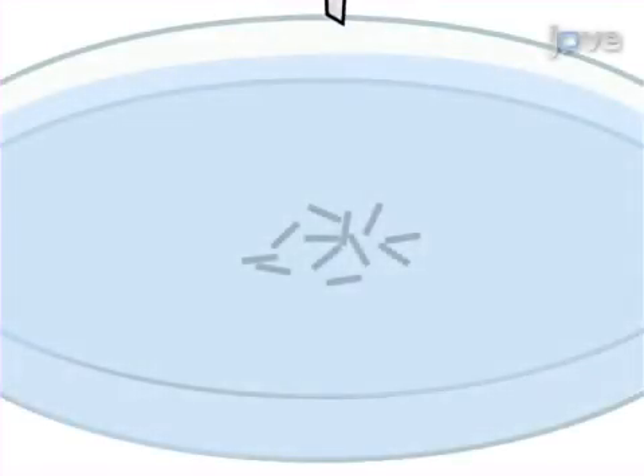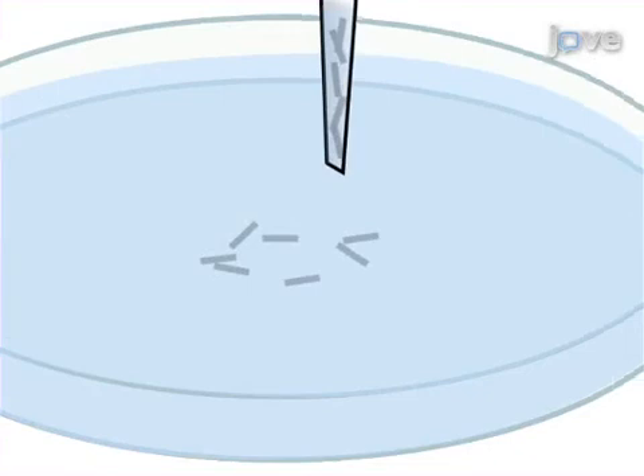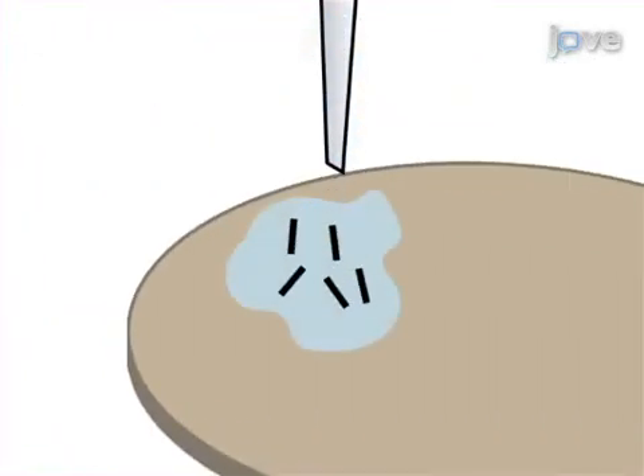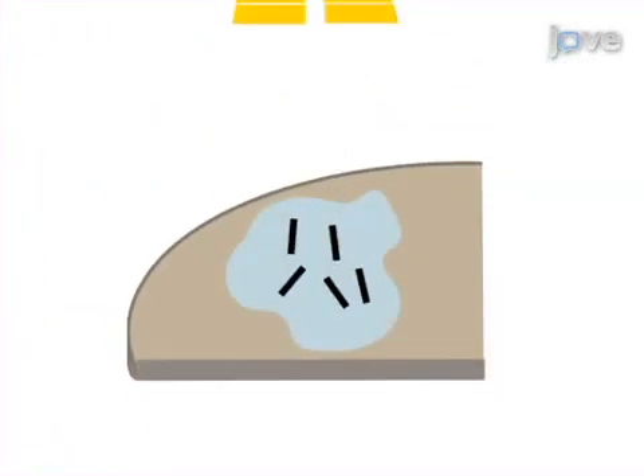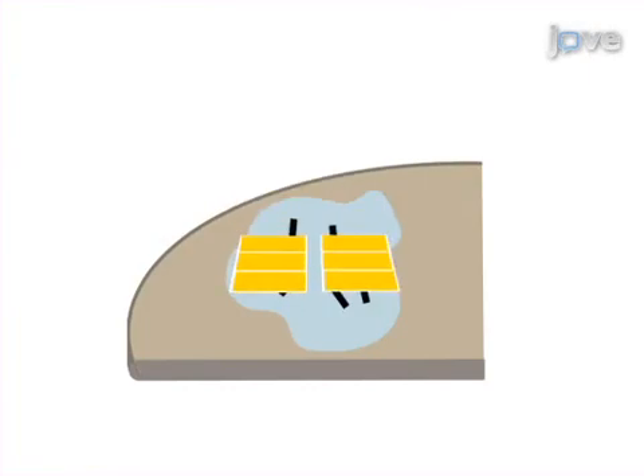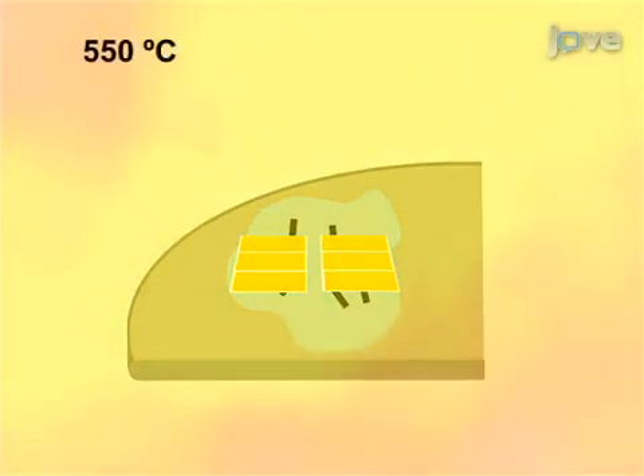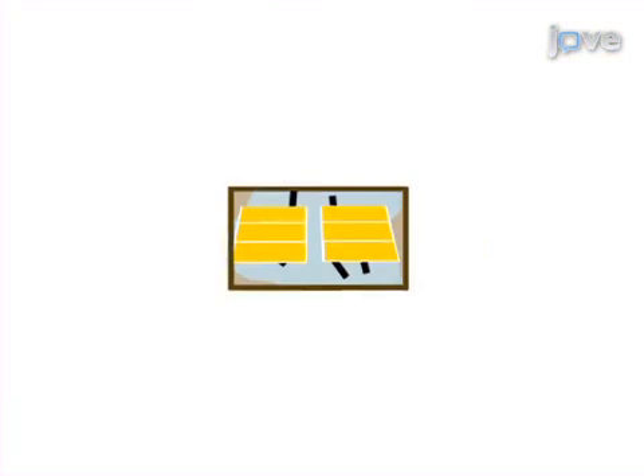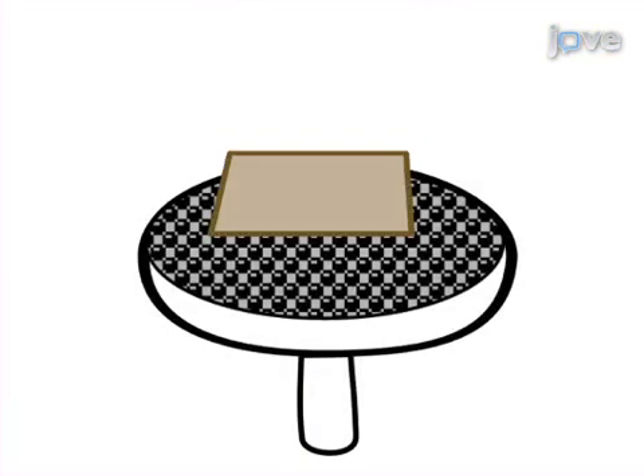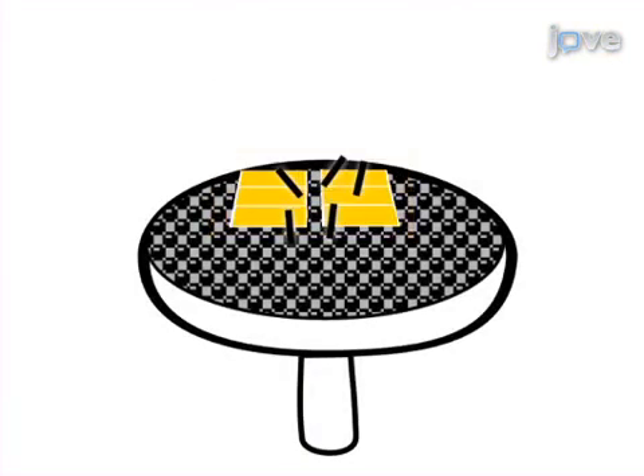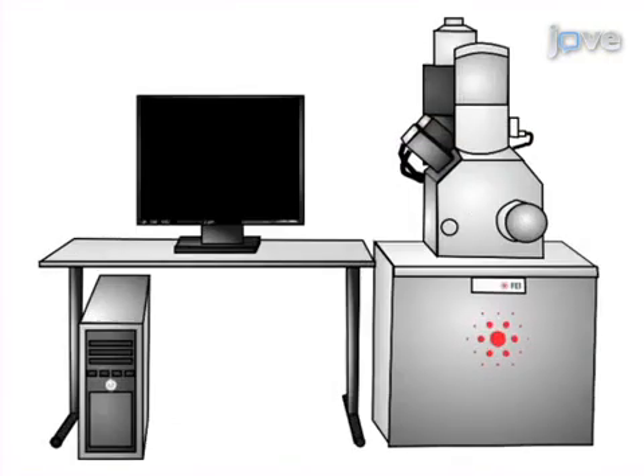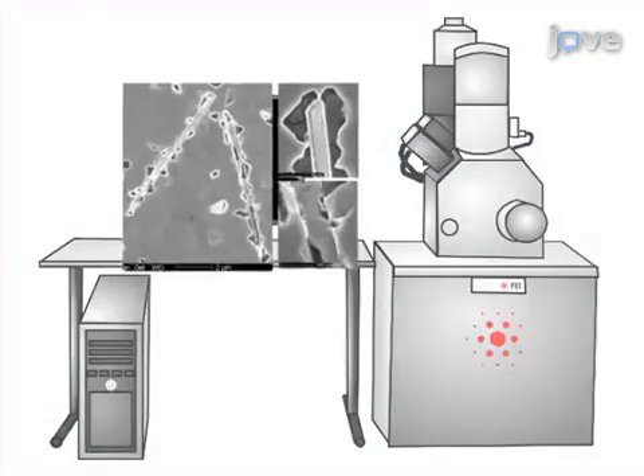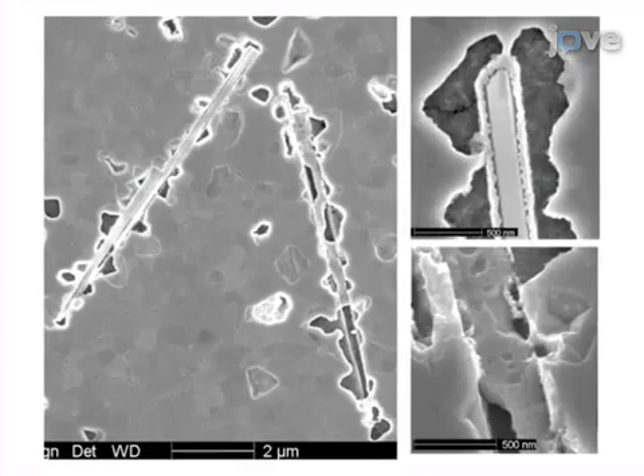This is accomplished by first preparing a nanowire suspension and dispersing it onto a substrate. The second step is to deposit the nickel-gold contacts on the nanowires and then anneal the sample. The final step is to remove the annealed nickel-gold contacts from the substrate by adhering them to carbon tape. Ultimately, a scanning electron microscope is used to examine the contact interfaces for void formation.